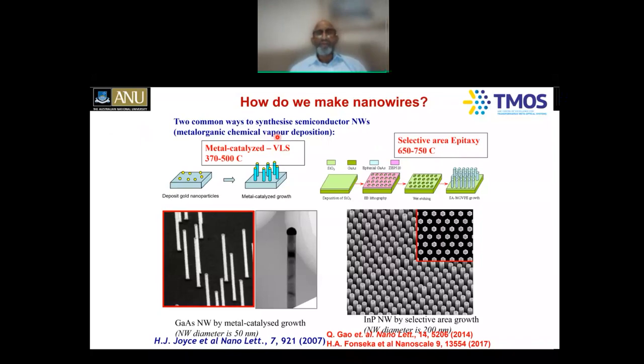I put a droplet of gold nanoparticles, which you can buy as colloidal solutions these days, 50 nanometer gold nanoparticles, onto the substrate, then put it into the MOCVD reactor and heat it up to between 370 and 500 degrees Celsius. The substrate is a gallium arsenide substrate. Normally gold has a very high melting temperature, more than 1000 degrees Celsius, but once it reacts with gallium or aluminum or indium, its alloy melting temperature comes down to as low as 350 degrees Celsius. So the eutectic liquid forms.